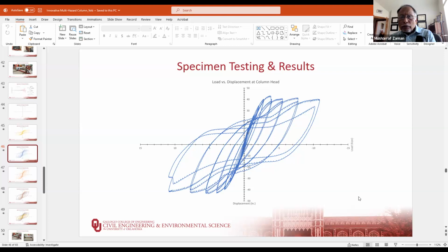The next question is, how is corrosion eliminated for the steel tube from inside? That is an excellent question, and a question I've gotten a couple of times. It's a confined area, right? Now we're looking at using bare steel because we want to get the best bond with the concrete. Because you remember, the concrete is going to fill up the inside of the tube up to the top of the foundation, and the inside of the tube down to the bottom of the pier cap. You have to put a plug in there to stop it from filling it up. But now it's a confined space.